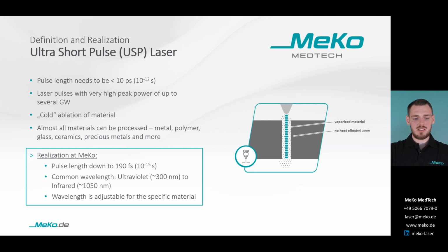As the material passes directly from the solid to the gaseous phase, there is not enough time for the energy to be transferred as heat into the base material, which is therefore also called cold ablation. This cold ablation enables us to cut the material without destroying the molecular integrity of the material. The polymer chain length as well as orientation is almost not affected by the process.